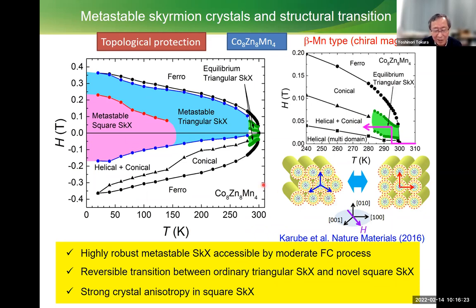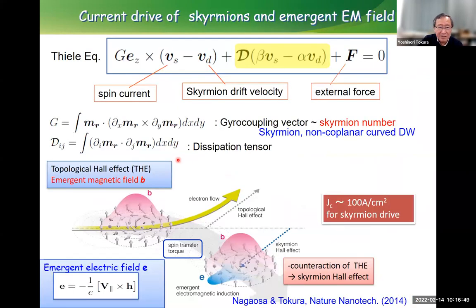But the metastability of the skyrmion is very good. We can just apply a very tiny magnetic field and just cool down. And then we can keep this magnet in our pocket, go to the neutron scattering center, and the crystal is already full of skyrmions, right? It's stable. So another important point is skyrmion dynamics. It's very easily driven by current. And usually this kind of spin texture